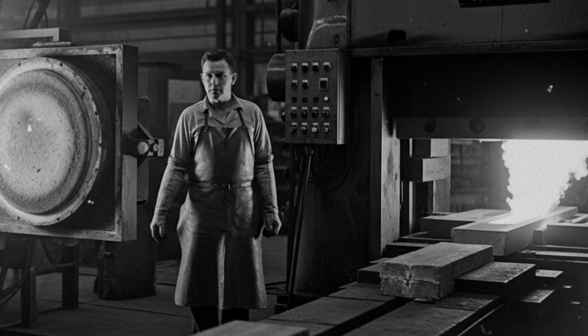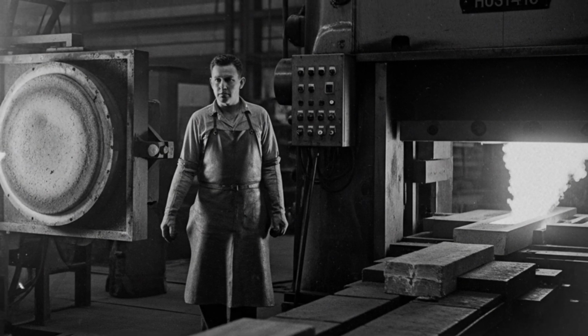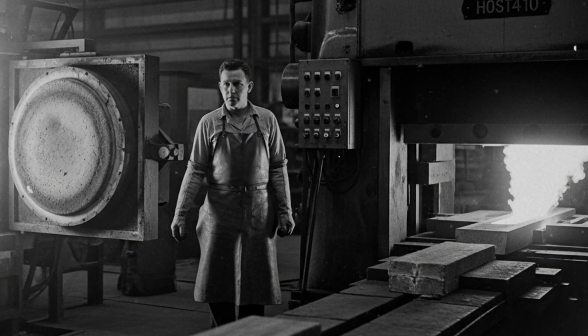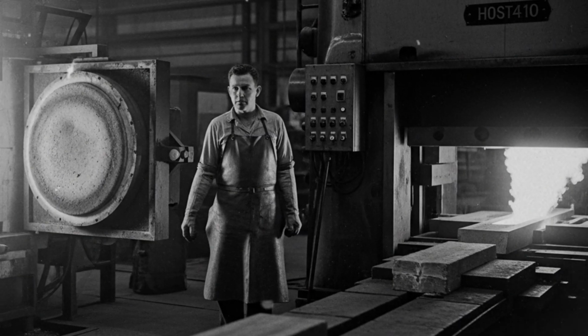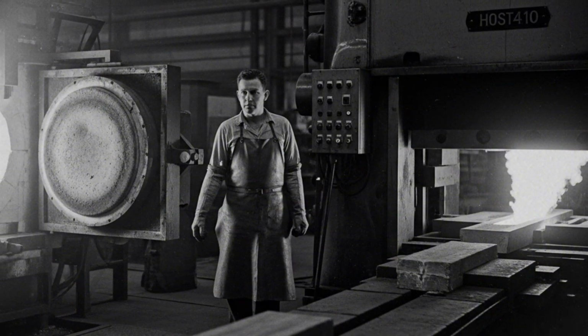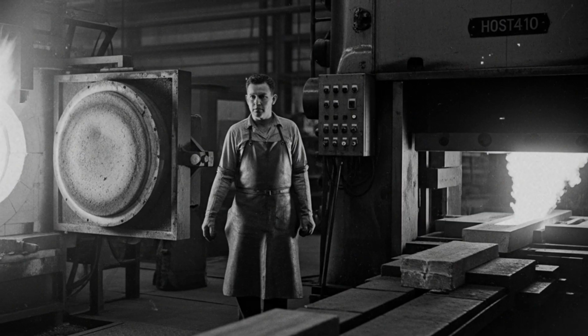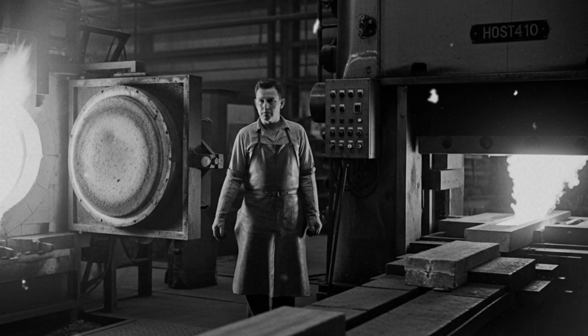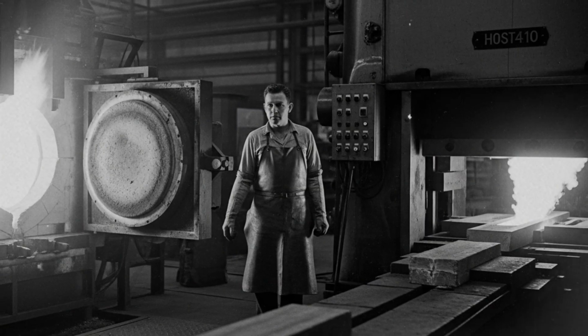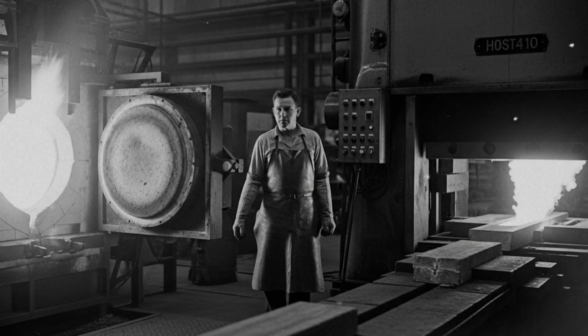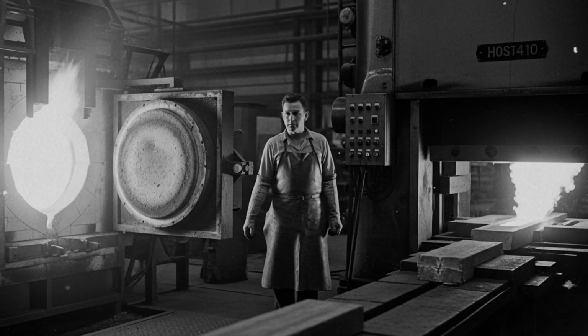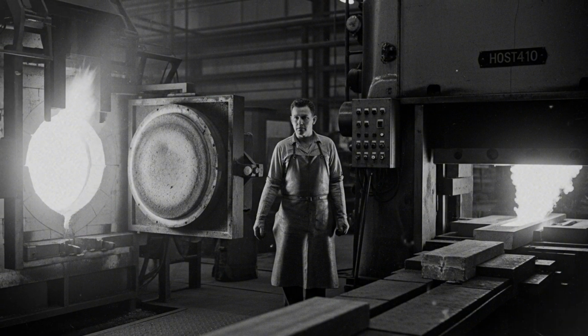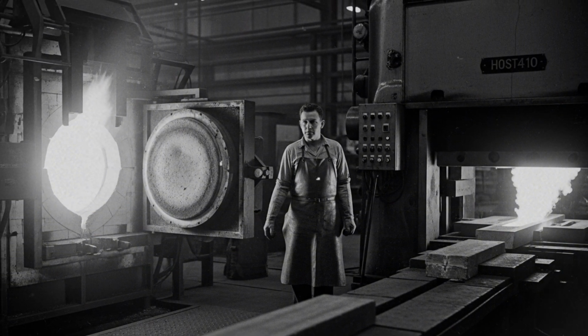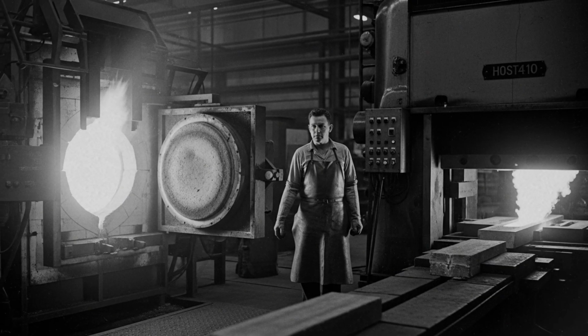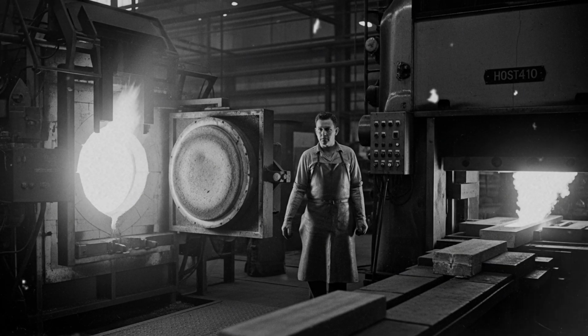Too hot, and the alloy's microstructure degrades, with grain growth and incipient melting at grain boundaries producing a part that meets dimensional specifications while failing the metallurgical ones. The furnaces that heat billets to forging temperature are located adjacent to the press, close enough that transfer time, the interval between billet extraction and die contact, does not allow excessive temperature loss. But this proximity means that the operators working the press floor are working in an environment where radiant heat from both the furnace doors and the heated billets contributes to ambient temperatures that, at the die face during active production, routinely exceed 110 degrees Fahrenheit.